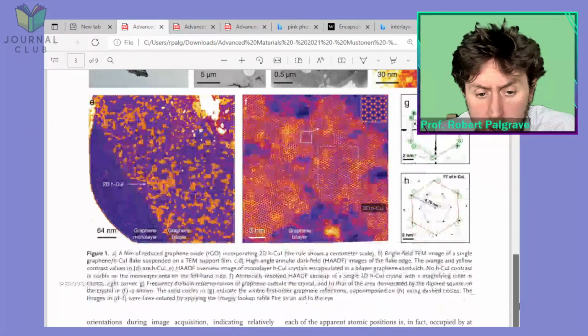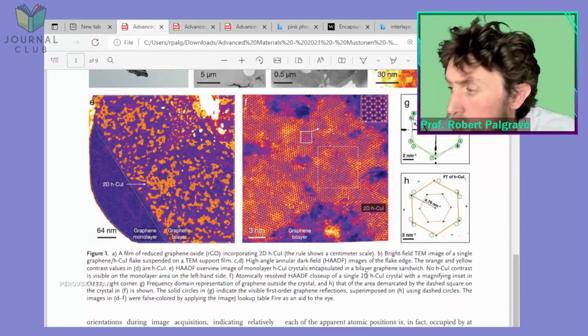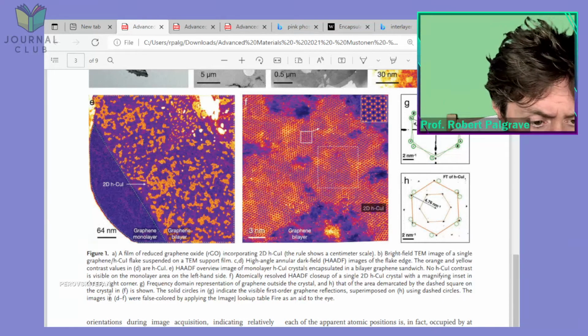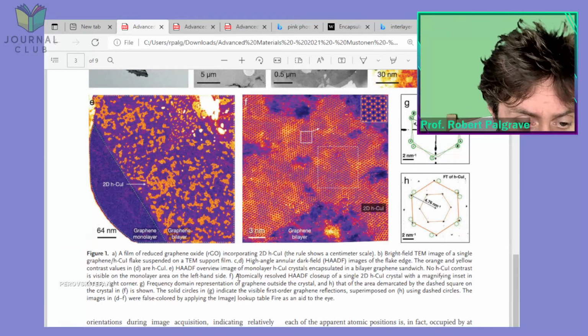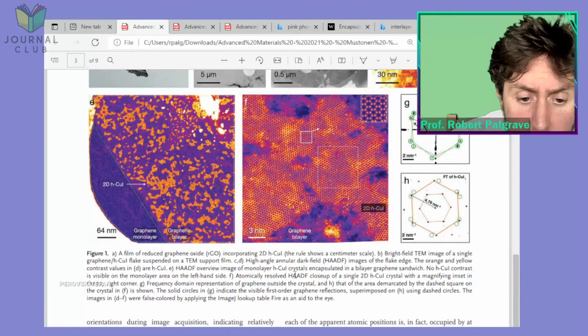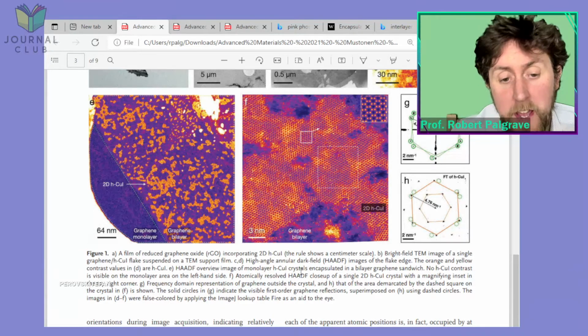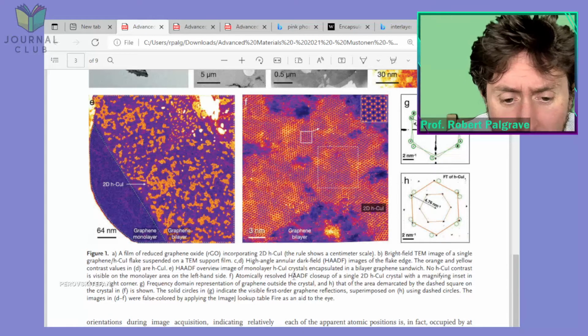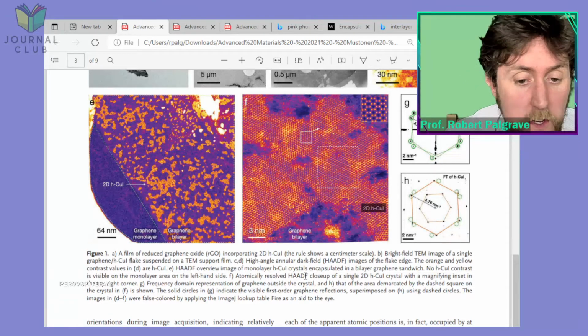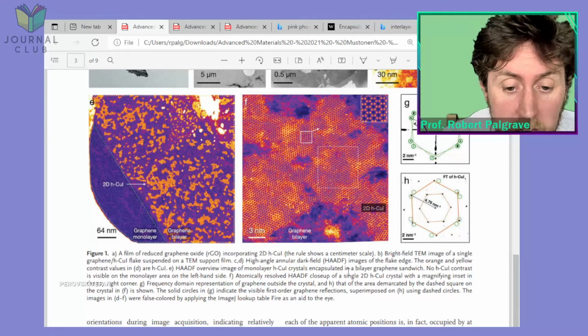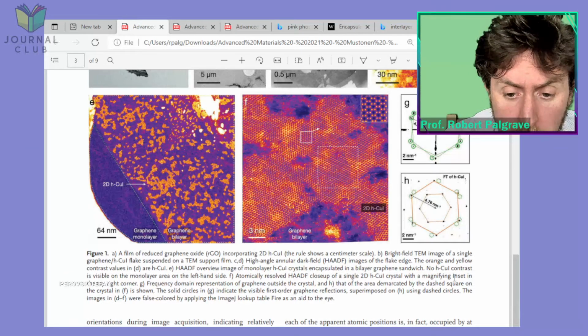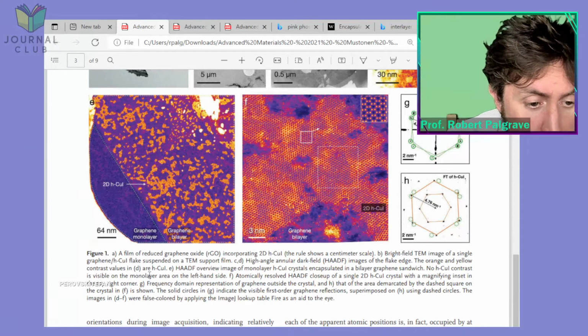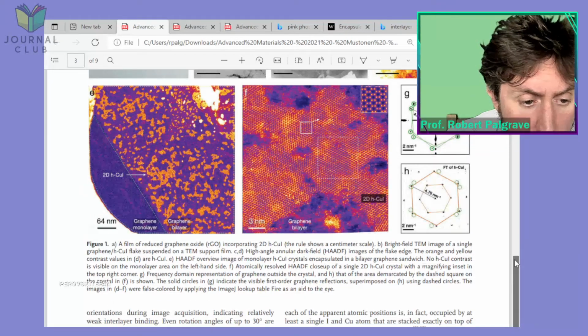Scroll down slightly. Where is F? So D to F are false colored. Okay, F, atomically resolved HAADF. So HAADF is a kind of TEM, high angle annular dark field, I believe is what HAADF stands for. Close up of a single 2D hexagonal cuprous iodide crystal with magnified inset in the top right corner.